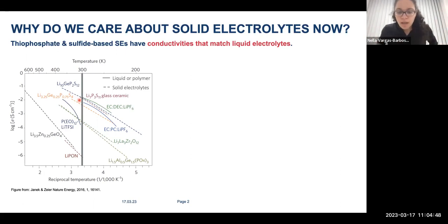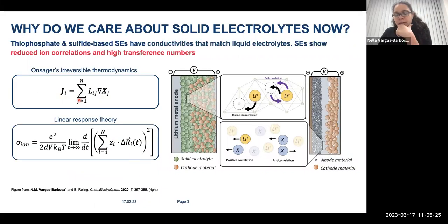This opens a whole new world of possibilities, because now we can replace the volume occupied by the electrolyte with just a solid material. There's also the thought of safety: liquid electrolytes have flammable components, and in principle a solid is less flammable. There's more research showing solid electrolytes aren't dramatically safer, but in general that's one idea. The second benefit is that ion transport is significantly simpler in a solid electrolyte—we only have a single moving species.